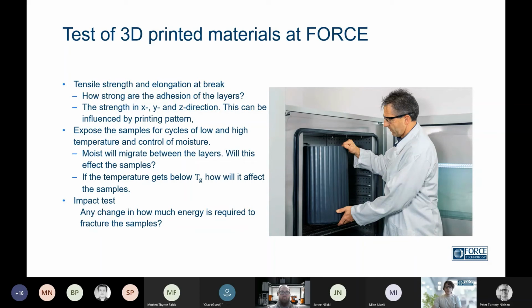What we also can do is expose samples for cycles in what we call the climate chamber, where we have the opportunity to control the temperature and the humidity of the air, and it can also go below freezing points. So we can see the effect of what would happen if we expose our products to high humidity, so moisture can migrate between the printing layers, and then we can see how this will affect the performance.